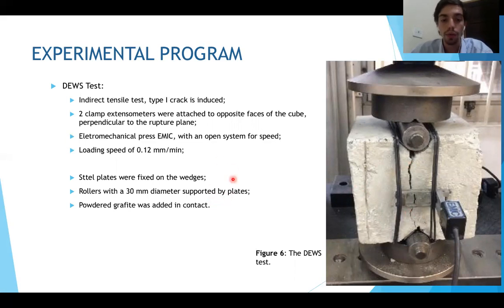An electromechanical EMIC press with an open system for speed was used, with a loading speed of 0.12 millimeters per minute. To avoid interference with the results, a 3 centimeters diameter steel roller is used between the press and the specimen, supported by the surfaces molded by the wedges. On these surfaces, steel sheets are fixed and powdered graphite is spread to reduce friction.